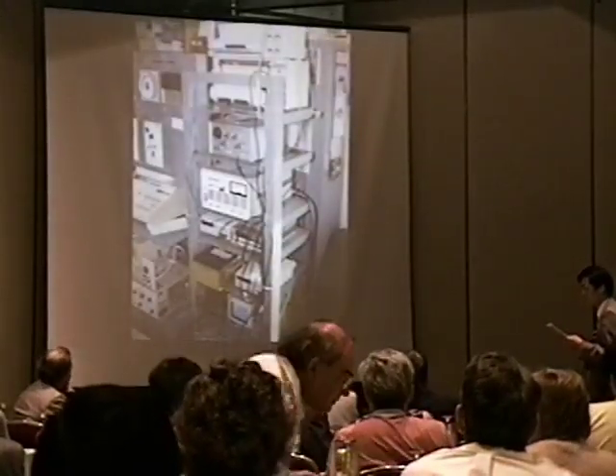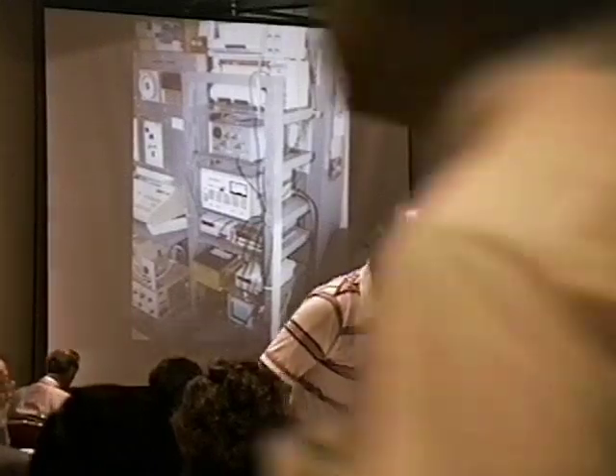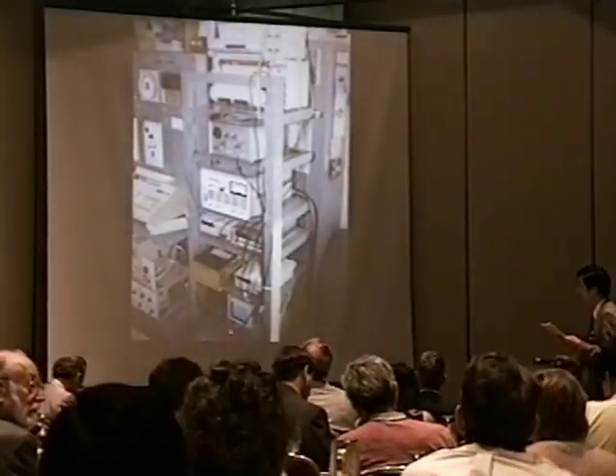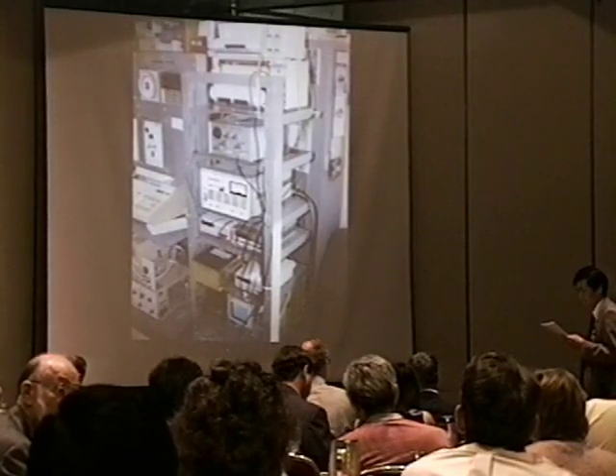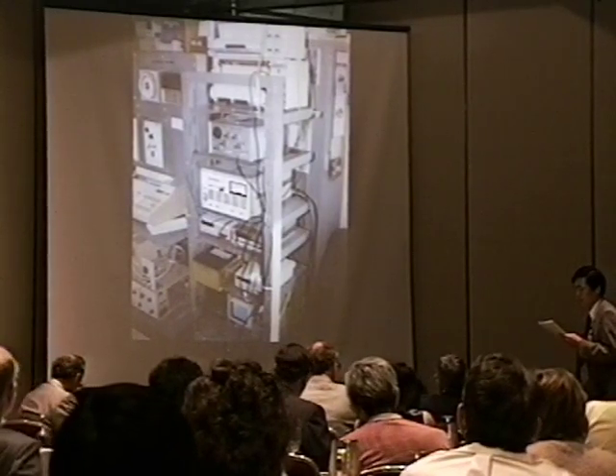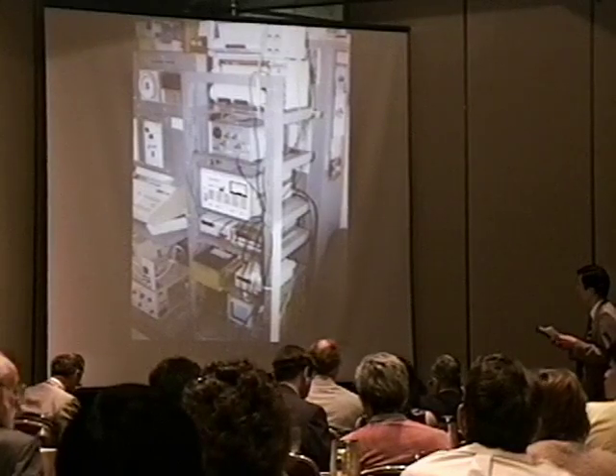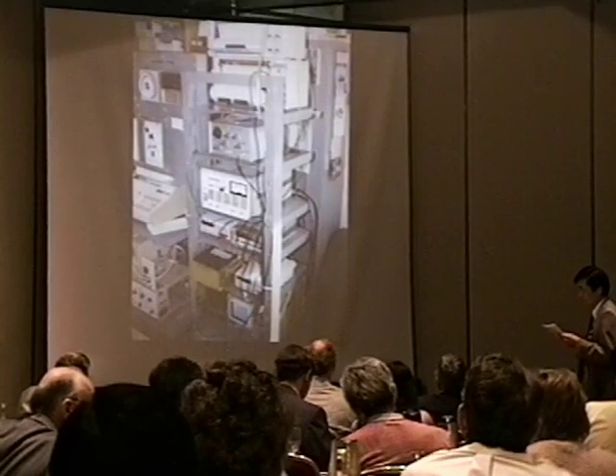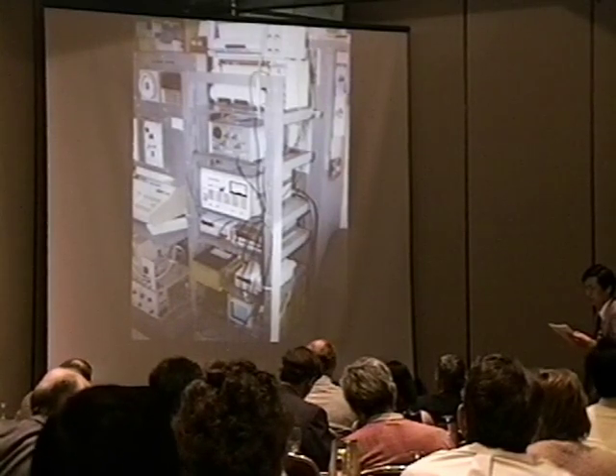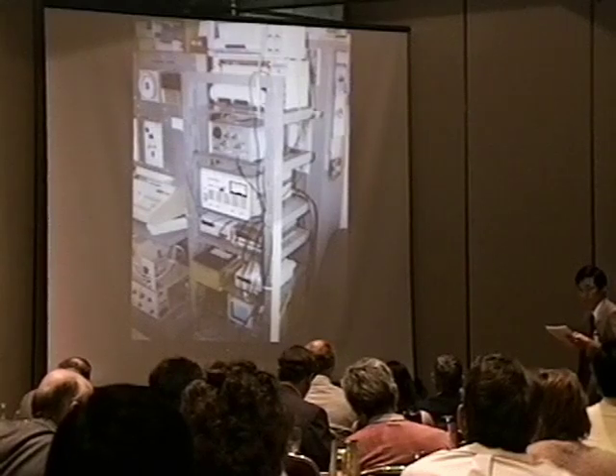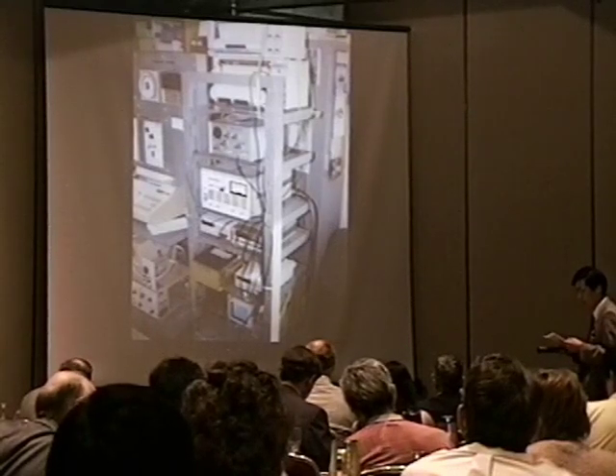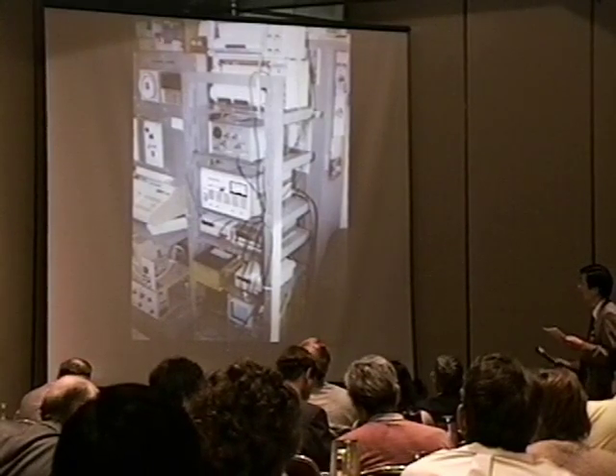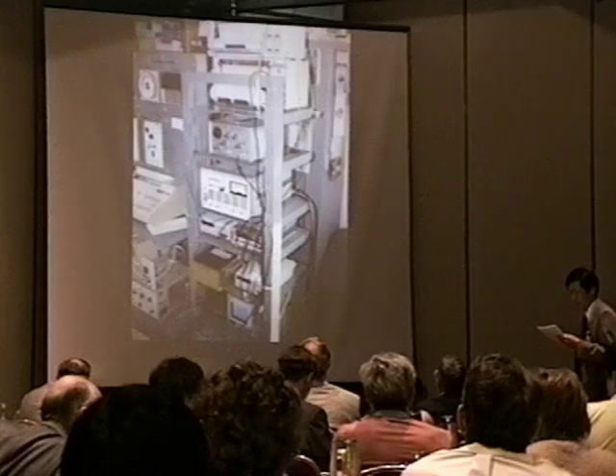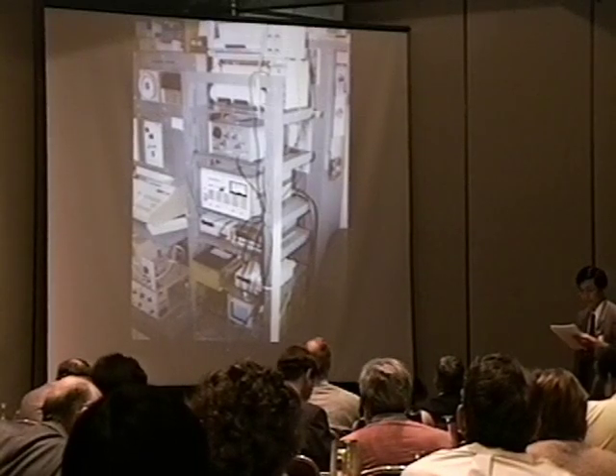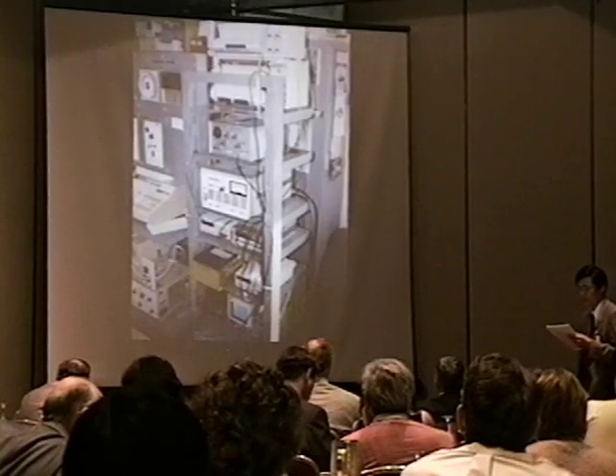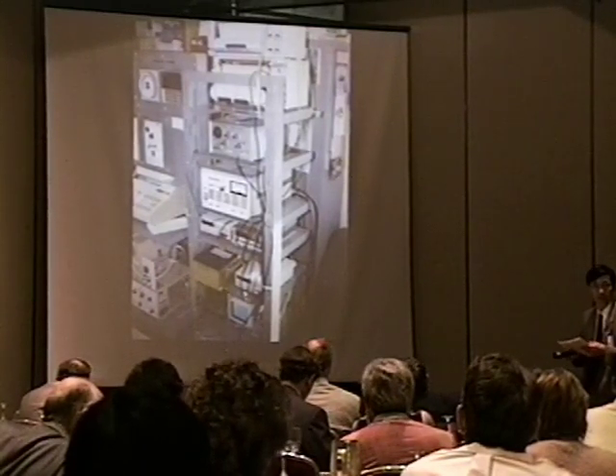This shows the temperature measurement system. The sample is kept at a constant temperature by means of the stabilized power supply. The electric power is recorded continuously by means of a pen recorder and 2 digital voltmeters for current and voltage. Temperature was recorded by means of a digital voltmeter to 0.1 degrees centigrade. The pressure in the vessel was measured using a pressure to voltage transducer. The temperature versus input heater power relationship was calibrated for various gas mixtures.